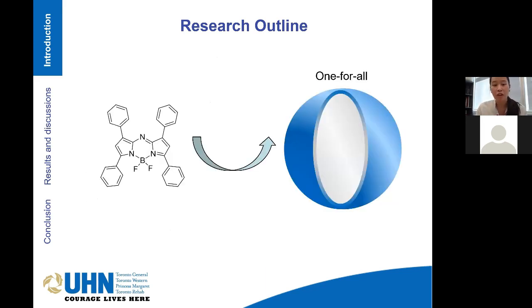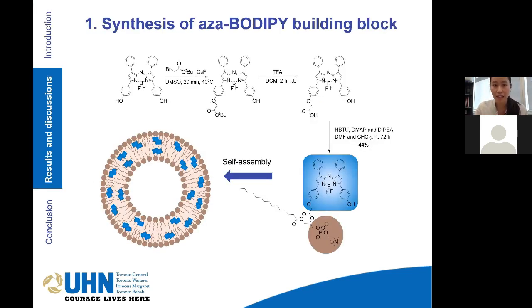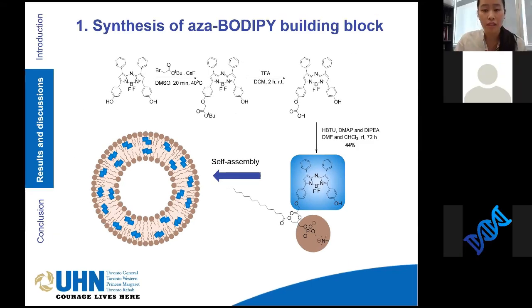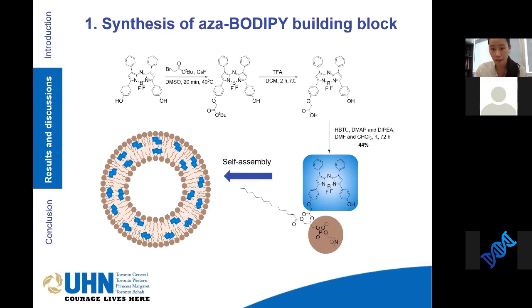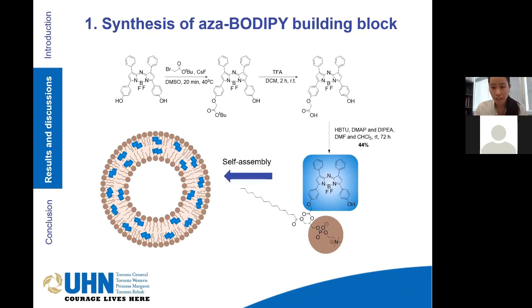My mission, therefore, is to put these aza-BODIPY molecules into a one-for-all nanoparticle. In order to do that, the first thing I did was to synthesize an aza-BODIPY building block. I went through a series of reactions where I can modify the phenolic ring of these aza-BODIPYs and conjugate it to a C16 phospholipid chain. This results in an aza-BODIPY lipid, and this aza-BODIPY lipid can then self-assemble into liposomes, which we're calling here bodopisomes.